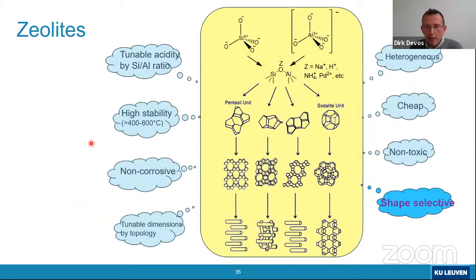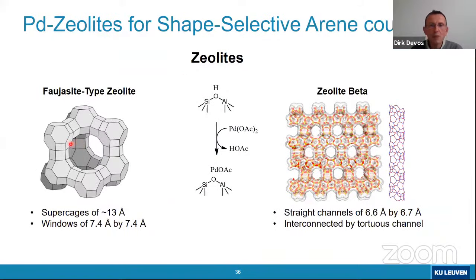So we had the idea that maybe it could be interesting to use zeolites in these palladium catalyzed reactions. And I'm not going to tell the whole story, but indeed we started to look at arene coupling reactions, for instance, coupling of two toluenes to make bitolyl in the presence of zeolites. And initially we had envisioned that these zeolites could replace the strong acid co-catalysts, like for instance p-toluenesulfonic acid, that are often used in these reactions. So that was the outset of our research. We thought, well, let's just use a solid acid instead of the homogeneous acid.